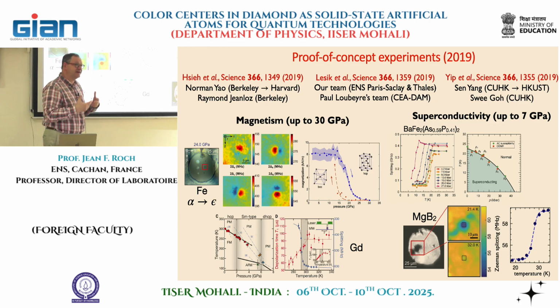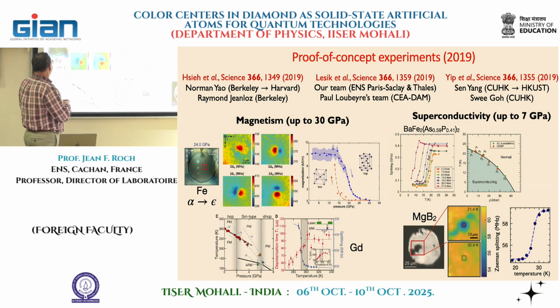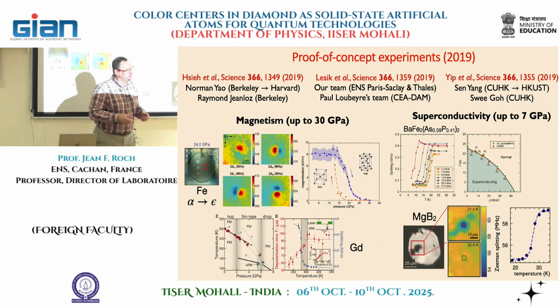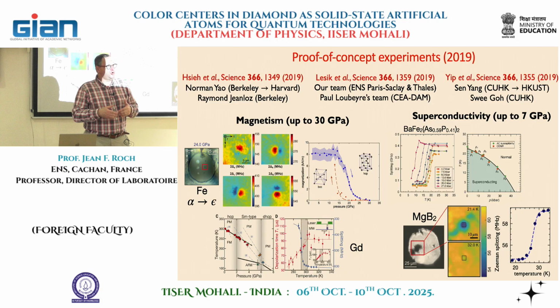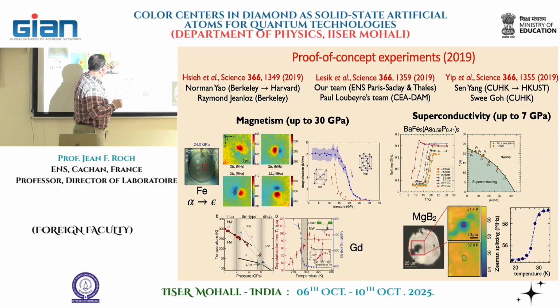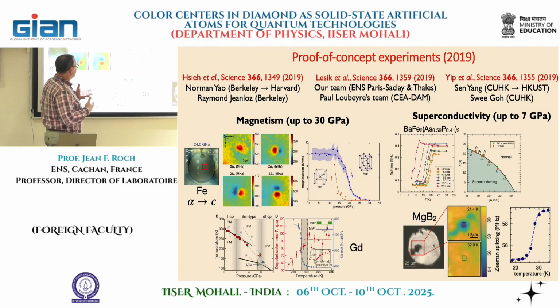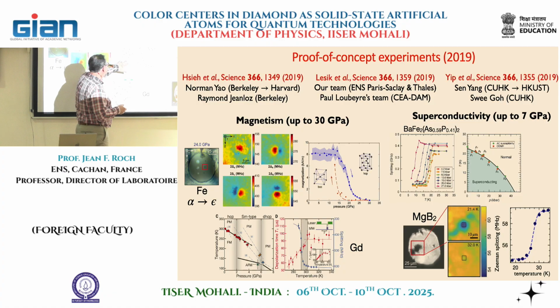So it's always a combination of people that have knowledge of NV centers plus people having the knowledge of high-pressure techniques. So in our case, for instance, what we did was to investigate a well-known pressure-induced transition occurring in iron. So if you have iron, you know that iron in our conditions can be ferromagnetic, and that's associated to this specific crystallographic structure. But now if you go to higher pressure, even at ambient temperature, you go to this new phase of iron, and in this phase, there is not anymore ferromagnetism. There is no magnetism at all, and the reason is not completely clear, even now. So there are a lot of studies to understand the reason for that. Nevertheless, we said this is a nice testbed system.